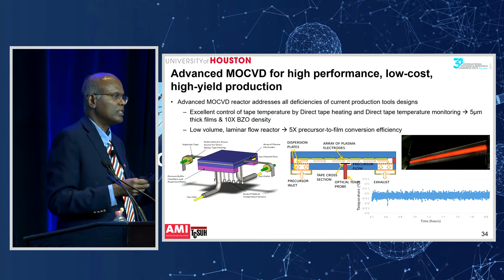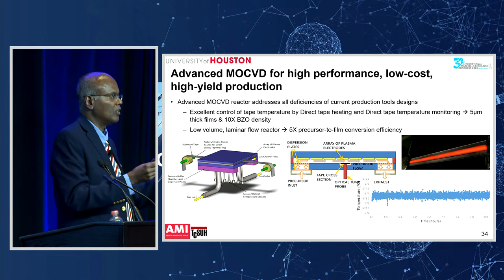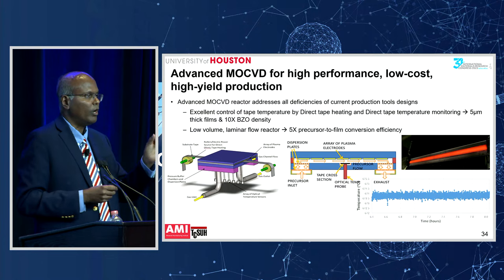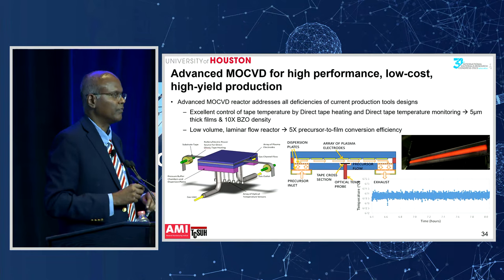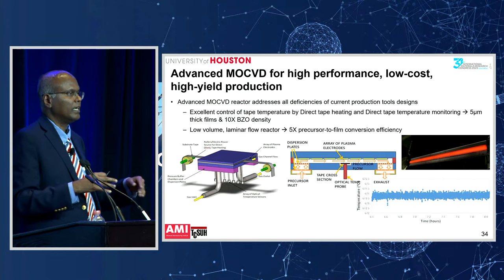So we actually pump current directly into the Hastelloy, which means the Hastelloy can be heated directly without using any heater. So now we can monitor the tape temperature directly with optical probes, and we can control the tape temperature really well. We remove the showerhead, we have nice laminar flow, and that controls the flow much, much better than what we had before. So by using these two methods, you can see very good temperature control, very good flow